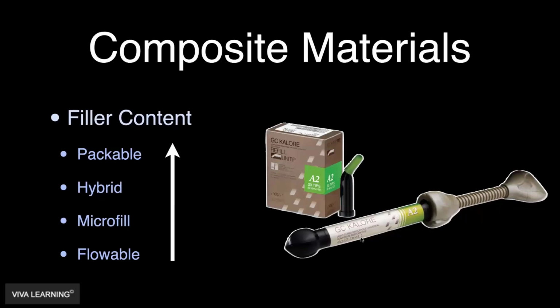And you could still basically tell the filler percentage by the viscosity. So if you put them out on a mixing pad, and as you're injecting it, it's just becoming sort of this big flat lake. Very low to no filler percentage. If you could actually inject it out and you could almost shape it like a soft serve ice cream cone, and the slower it slumped, the higher the filler percentage was. So you could still use that as a general rule of thumb.